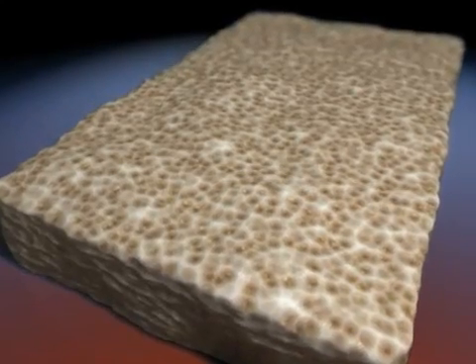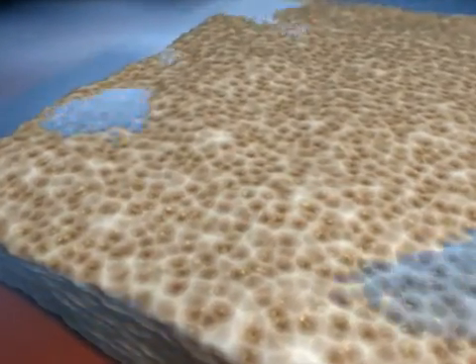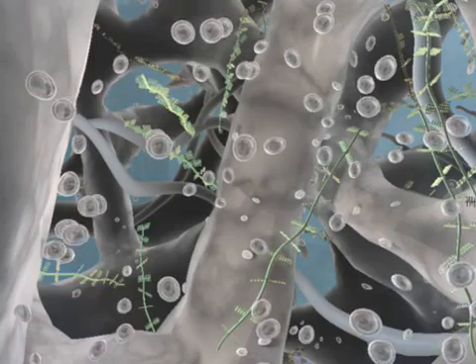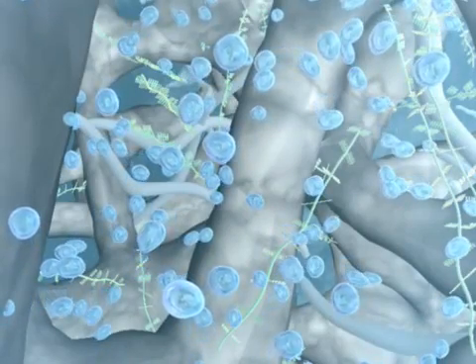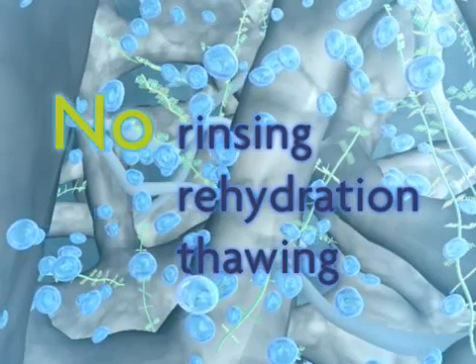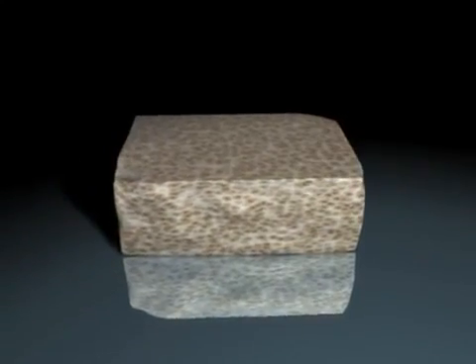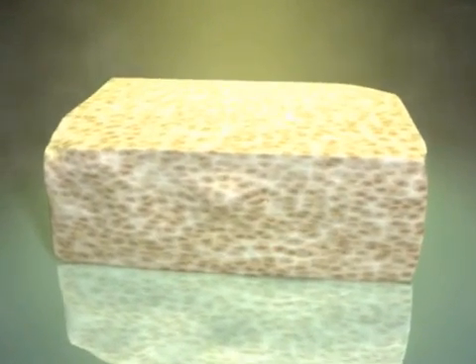Isotonic saline rinses out cellular components and removes the decellularization reagents. The allograft is bathed in a LifeNet Health proprietary USP glycerol solution. This preservation agent is a naturally occurring molecule and acts as a water replacement agent, enabling convenient room temperature storage, allowing the product to be used immediately without rinsing, rehydration, or thawing. The final step is sterilization with low-dose gamma irradiation at dry ice temperatures, which results in a sterility assurance level of 10 to the negative 6 while maintaining the biomechanical integrity of the tissue.